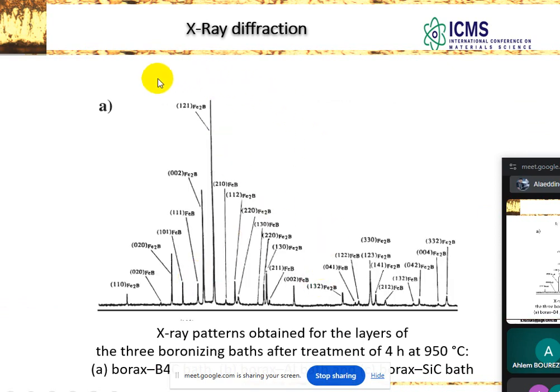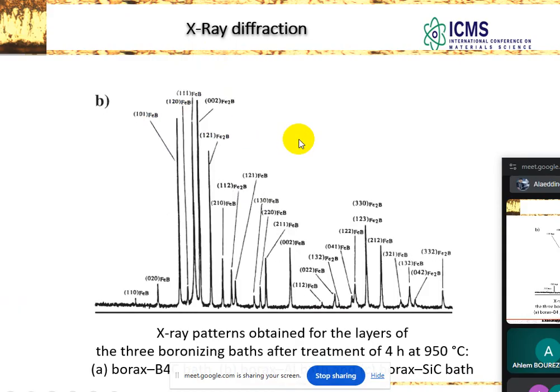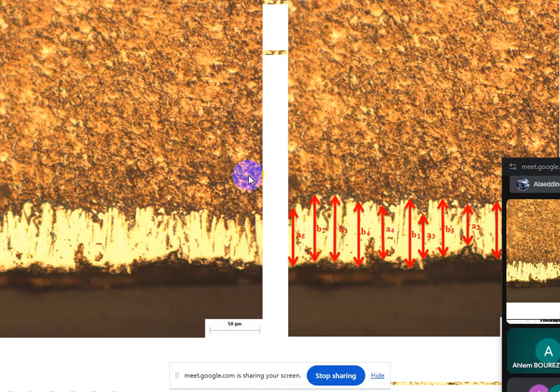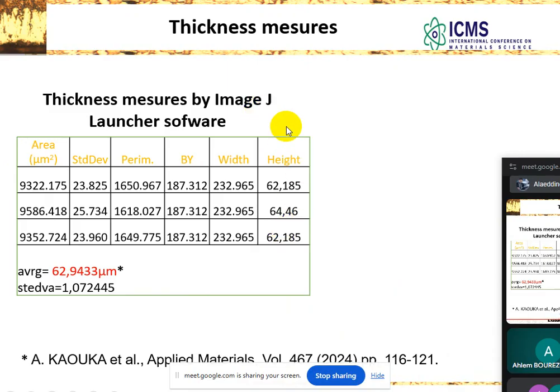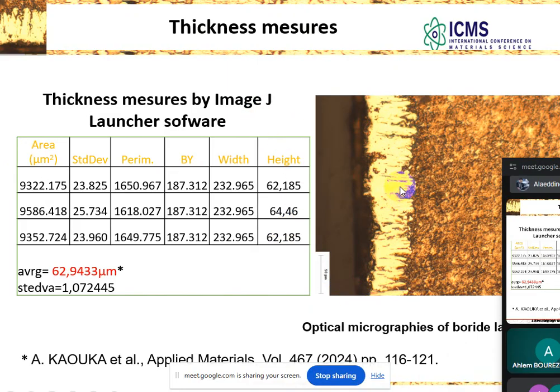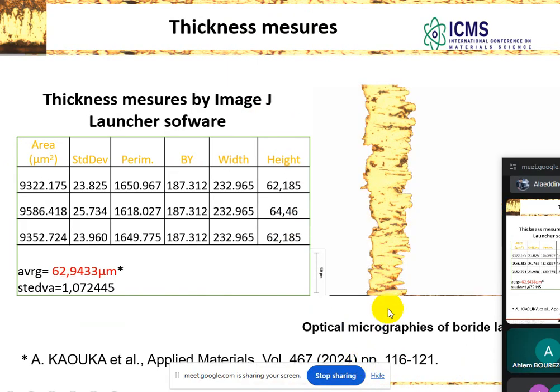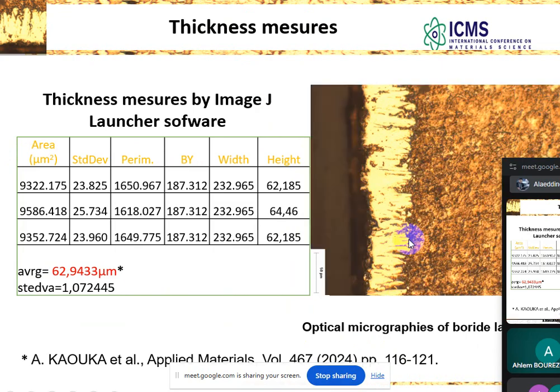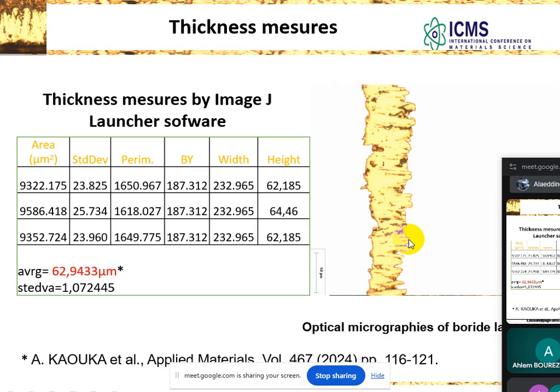So this is the X-ray diffraction peak to confirm that we have the phases of iron boride and iron 2 borides at different temperatures and different chemical compositions. After that, we try to measure the thickness of the boride treatment. This is the traditional method. So we use a new method using ImageJ software, which is free. You can download it from the internet.